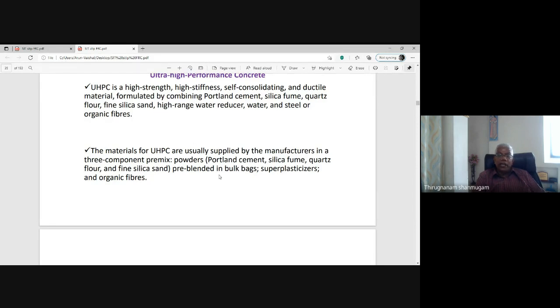So the fabrication or the casting is easy. You just mix the powder with the required amount of water with superplasticizer, and the fibers are randomly distributed over this matrix. It produces the ultra high performance concrete. This is a reactive powder concrete, RPC. Fine material only, coarse aggregate is not allowed.